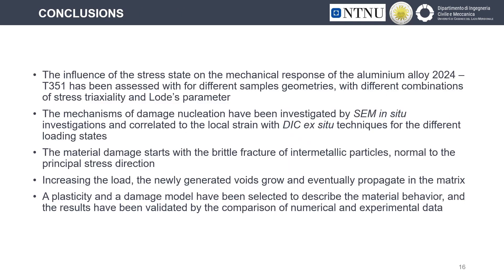In this work, we investigated the influence of the stress state on the mechanical response of aluminum alloy 2024, using different sample geometries which realize different combinations of stress triaxiality and Lode parameter. We also investigated the mechanisms of damage nucleation with SEM in-situ investigation and DIC techniques. Material damage starts with the brittle fracture of large intermetallic particles normal to the principal stress direction, and the newly generated voids grow and propagate into the matrix, causing the final failure. From the experimental results, we proposed and validated a plasticity and damage model that accounts for the shear sensitivity of the material, and validated it by comparison of numerical and experimental data.